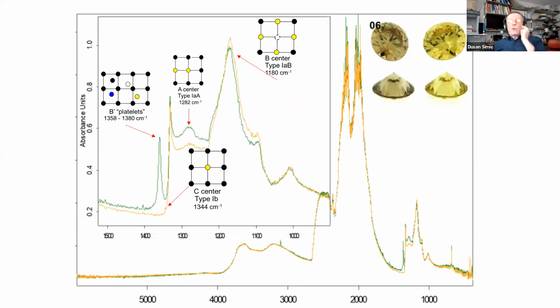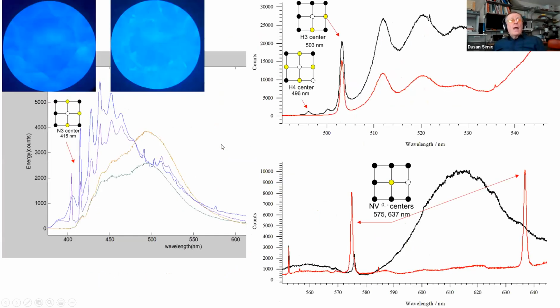Here is another stone, starting brown color and then yellow color. And also I have to say that the brown is not completely removed. There is still some brown, okay? This is a significant improvement, but the brown is not completely removed. What we see here is that the platelets, the interstitial atoms, are all removed, you know. Okay, not a big deal. This is not so stable a center. Also, some decrease in the A center, and creation of the N3 center.